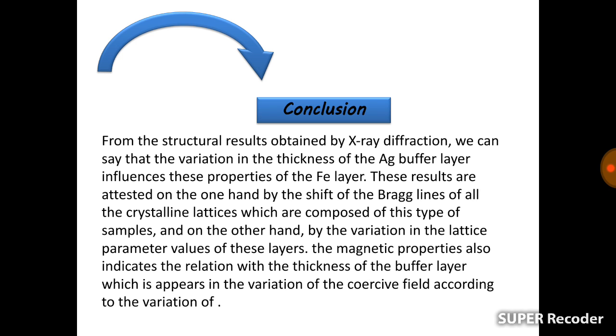Finally, in conclusion, from the structural results obtained by X-ray diffraction, we can say that the variation in the thickness of the silver buffer layer influences the properties of the iron layer. These results are attested on the one hand by the shift of the Bragg lines of all the crystalline layers which compose this type of samples, and on the other hand by the variation in the lattice parameter values of these layers. The magnetic properties also indicate a relation with the thickness of the buffer layer, which appears in the variation of the coercive field according to the variation of the thickness.